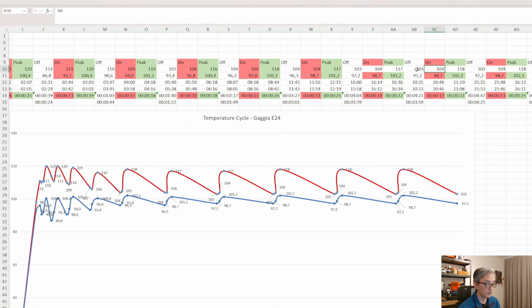The consequence is that the peak is not 126 degrees anymore in the boiler, and this on and off means that the heating element is activated for a shorter period of time, and then you have more stability, you have less amplitude in the temperature in your boiler, and as a consequence in your water. And this is why this curve here is flatter than in my Gaggia Classic. This is why it's more stable.